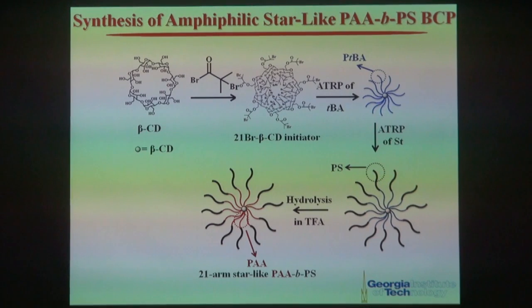So in our group, we thought we wanted to study this. We want to create such unimolecular micelle-like structures based on star-like block copolymers. So we recently synthesized a set of amphiphilic star-like block copolymers. The first one is this 21-arm star-like polyacrylic acid, PAA, block polystyrene, PS. We started off by reacting beta-cyclodextrin, beta-CD, which possesses 21 hydroxyl groups on the surface, with this small molecule, yielding this 21-bromo-beta-CD macroinitiator. Then we took this macroinitiator and performed atom transfer radical polymerization of tert-butyl acrylate, yielding this 21-arm star-like poly(tert-butyl acrylate)